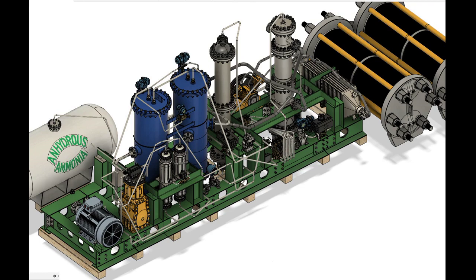Early ammonia converters, material challenges. Early ammonia synthesis converters made by BASF, constructed out of carbon steel during the 1910s, experienced catastrophic failures induced by high-temperature hydrogen attack. Failures were so common that engineers had to place the reactor vessels in concrete bombs or explosion-proof chambers to prevent damage to surrounding equipment or harm to personnel. It was only after Carl Bosch made use of chromium steel that the process could be commercialized.